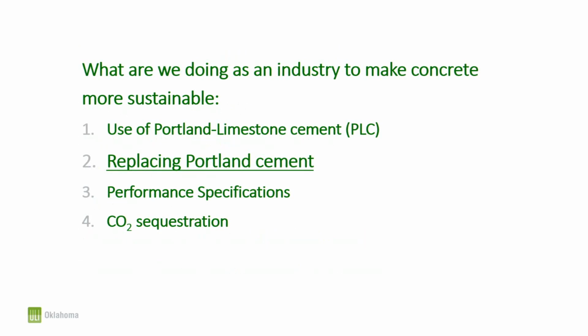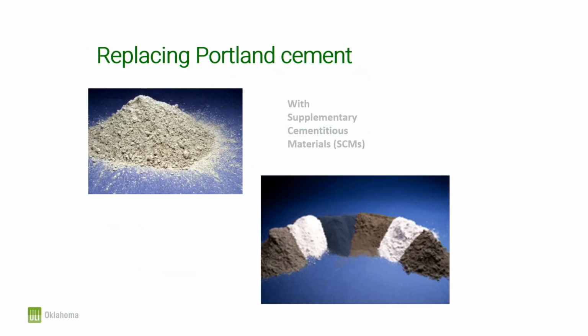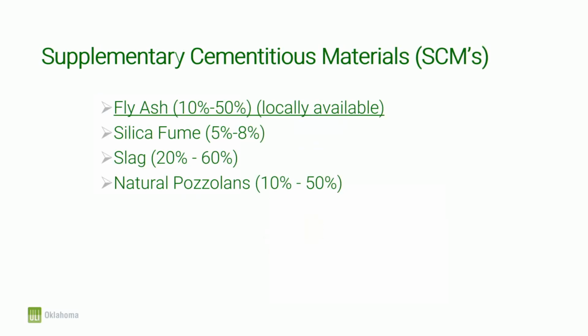What we're doing as well is replacing the Portland cement in a cubic yard of concrete. What we do is what we call supplementary cementitious materials. Some of the ones that we use here locally in Oklahoma, the big one is fly ash. Fly ash is a byproduct from the thermal plants producing electricity when they use coal. The power plants here in Oklahoma are starting to reduce the amount of coal that they burn, so we are having less and less of that fly ash available.